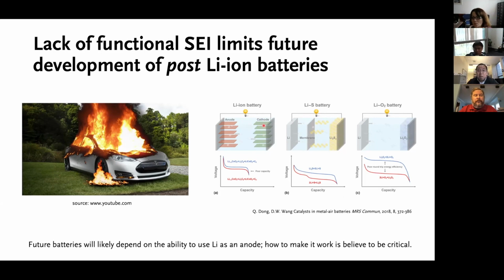And this is because, in order to provide reliable insertion and deintercalation, you do need transition metal whose oxidation state can be toggled without collapsing the structure. As a result, theoretically, this old concept can support a specific energy density close to 300 watt hours per kilogram. And that's a number important to remember because this is a number that will not meet our needs to electrify most of our cars, for instance. And of course, I'm sure you also have the moments where you have the anxiety of your cell phone battery running out. So in order to break the barrier, we need to switch to something different.